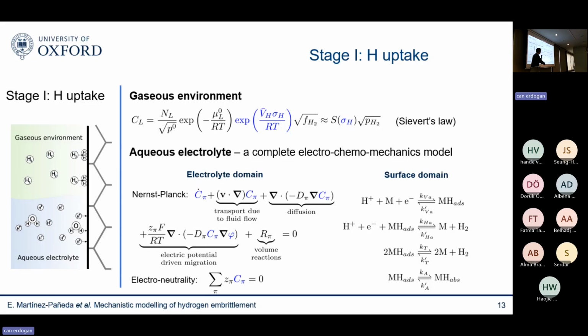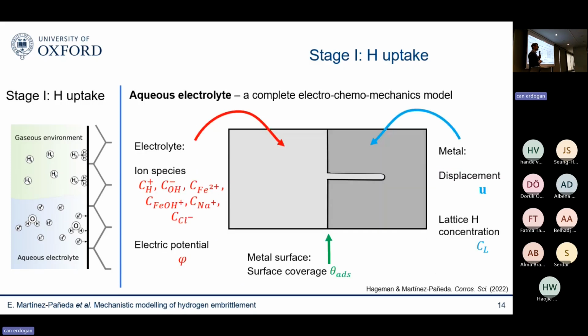Nernst-Planck equations, and these equations depend on diffusivity, on Faraday's constant, temperature, physical quantities, and then you can also resolve the hydrogen evolution and absorption reactions that are happening at the crack tip. So you can express this mathematically, you can implement this into your finite element code, and then you have a boundary value problem that looks like this, where you have an electrolyte where you're solving for as many ionic species as you need. Then you have a metal, which may contain a defect, where you're solving for your mechanical problem, for the hydrogen transfer problem, and then you're solving for some interface reactions in between.